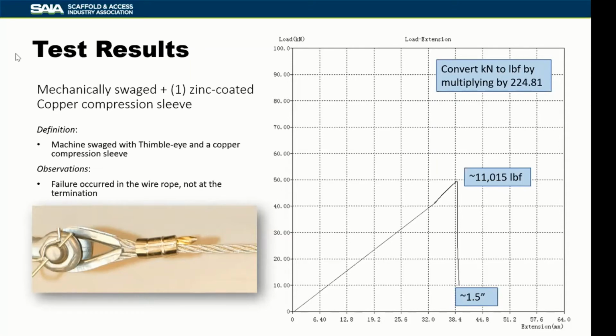In order to convert our millimeters to inches, you're dividing by 25.4, or a rough approximation is just dividing by 25. So for our first one, you see that we got about 11,000 pounds of force that it took to break the rope, and we had about 1.5 inches of extension. On this particular one, under the observations, you can see that the failure occurred in the wire rope, not in the termination. Although it is very common with the mechanically swaged terminations that the failure,